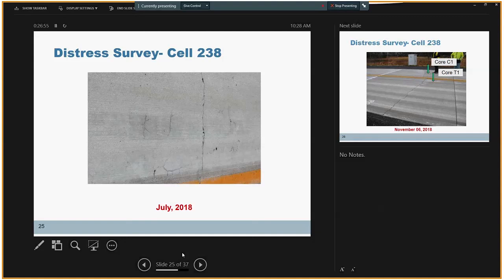I'm going to go through the distress survey. February 2018, we noticed a transverse crack in concrete pavement cast with lower cementitious material content, and this was followed by some spider-like cracks in July 2018.